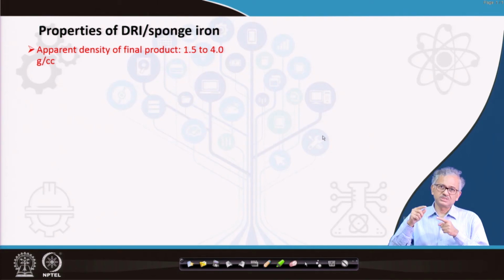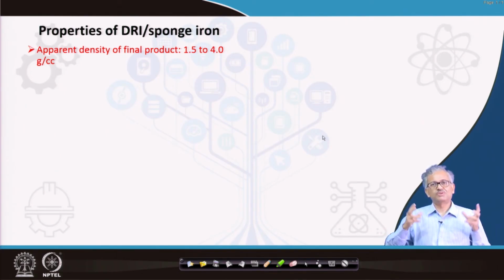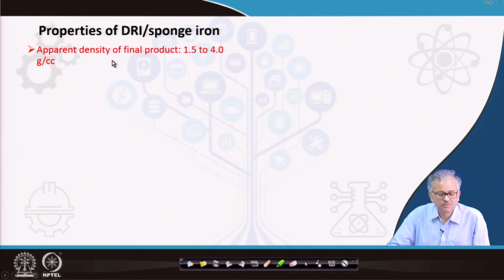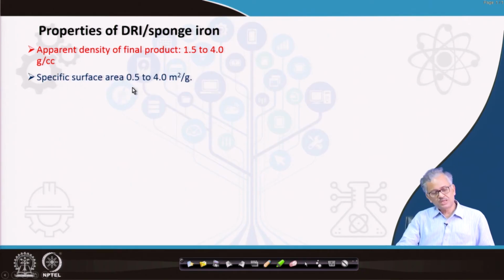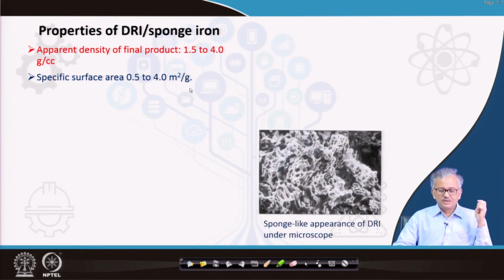Suppose you have 80% metallization, so 20% iron will remain in the form of wustite, okay, connected with oxygen. That oxygen also reduces the weight. Besides, the sponge iron contains a lot of micropores, so a lot of air is there inside. As a result, your apparent density is less, and depending on your metallization and the quality of the starting raw material, the density of the final product can be 1.5 to 4 gram per cc. And the specific surface area is quite high, 0.5 to 4 meter square per gram. You can see a very high specific surface area because of the presence of the pores inside it. Okay.